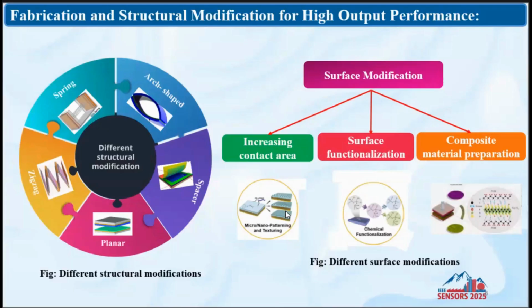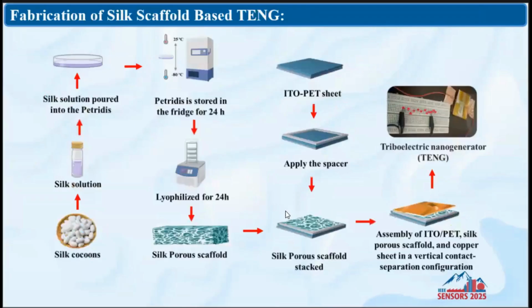And here we have selected increasing the contact area. For that, initially we developed a thin film based silk TENG, and we got a particular output voltage, but it's not enough for better or higher applications. For that, we tried to create pores. Now, if the pores increase, the surface charge increases. If the surface charge increases, the driving current will be more.